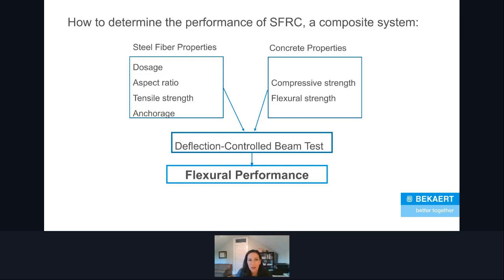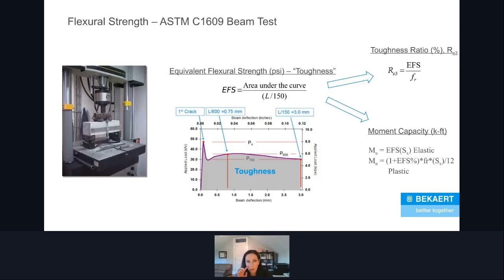Right? You take the steel fiber properties, your dosage, your concrete properties, you put them together, and we do deflection controlled beam tests. From this, we can extract flexural performance data. So here in the US, the most common test is the ASTM C1609. That is a test for fiber reinforcing in general. So it's not limited to steel fibers. You can see macrosynthetic fibers in there as well.